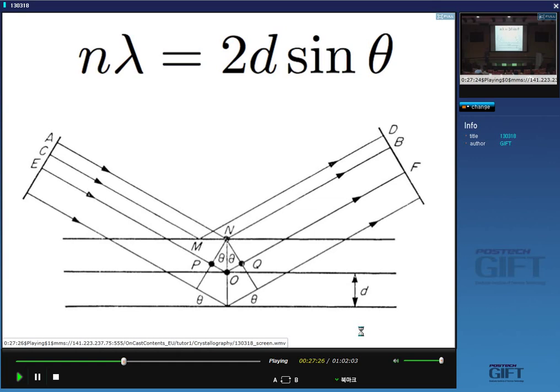You have to be able to go deep into the material to find another wave which will be half a wavelength out of phase when you deviate from the angle theta. The smaller the deviation, the deeper you have to go into the crystal. So if you are dealing with a thin foil, then the Bragg law will not be exactly satisfied. Even though you are not at the angle theta, you will get diffracted intensity because there's nothing underneath the thin foil to find a beam which is half a wavelength out of phase.